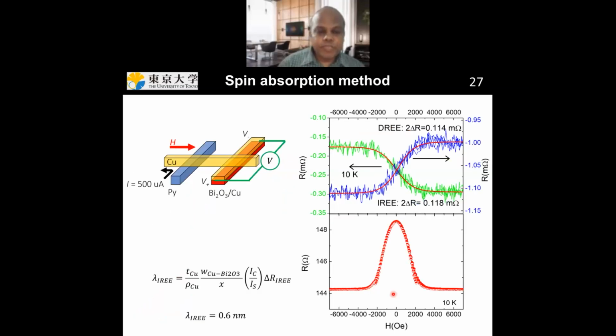Since we know that some of the spin current is absorbed by this bilayer, if you put a voltmeter, you should be able to detect some voltage due to the inverse Rashba-Edelstein effect. This blue curve shows the spin signal due to the inverse Rashba-Edelstein effect, similar to the one I explained earlier. Now I can calculate the inverse Rashba-Edelstein length using this formula. You know this one from this experiment, and the ratio between IC and IS you know from the previous experiment. From this, I calculated the Rashba-Edelstein length to be 0.6 nanometer for the bismuth oxide and copper bilayer.